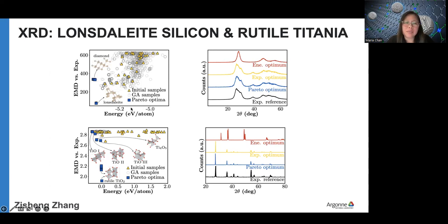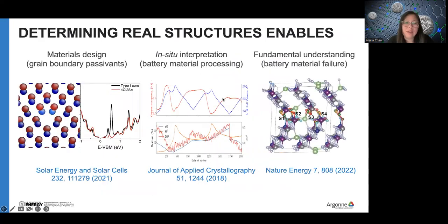It's interesting because you can see that there are some structures that are very high in energy, significantly higher than others, and some of them that match the XRD better. So I think one of the powers of this approach is we don't get one answer, we get a family of answers, and you can do simulation statistics and other analysis on them.